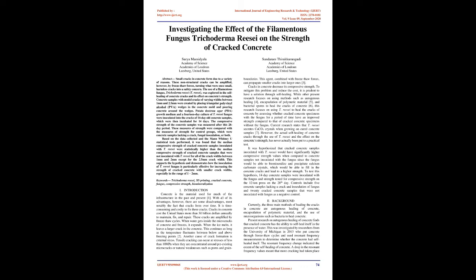This could be due to the fact that for larger crack widths, since the same amount of fungus was inoculated for each of the different crack widths, there was not enough biomineralization of the crack in proportion with the size of the remaining unfilled crack to cause the strength of the concrete to increase significantly.